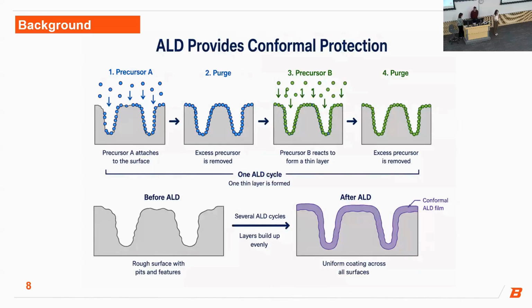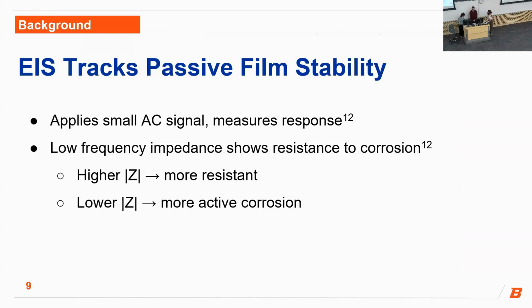So in order to address this, we are looking at a mitigation strategy. Specifically, we are looking at atomic layer deposition, or ALD. ALD can form thin conformal coatings that can coat even complex surfaces with rough features and pits. The schematic shows the ALD process where alternating precursors are reacting with the surface to create a thin film layer by layer. And after several layers, it can build a thin film that can uniformly coat even the rough surface.